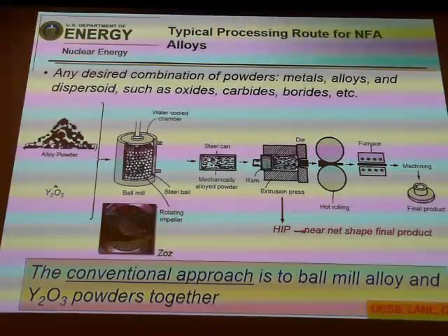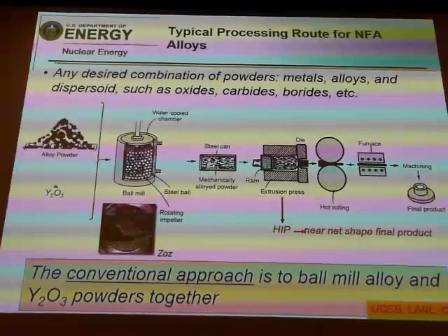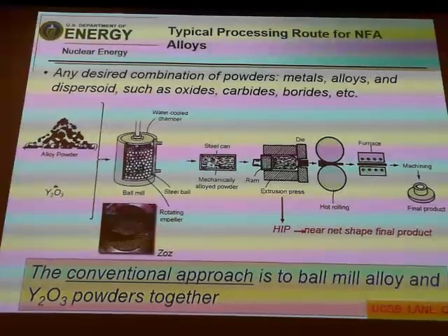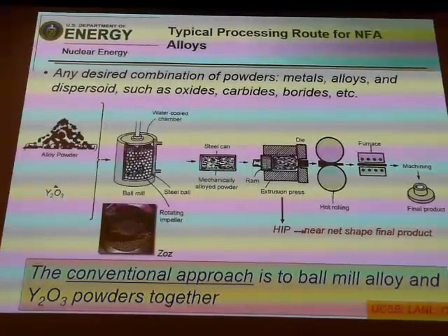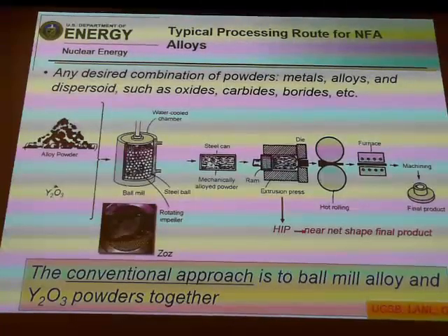So it doesn't want to go in solution, but you can force it into solution, and then once you do that, you either HIP it or extrude it. In this case we can it in a steel can and then extrude it at 850 degrees C, and then you can precipitate out those oxides in the location where the yttrium has gone into solution in the grains.